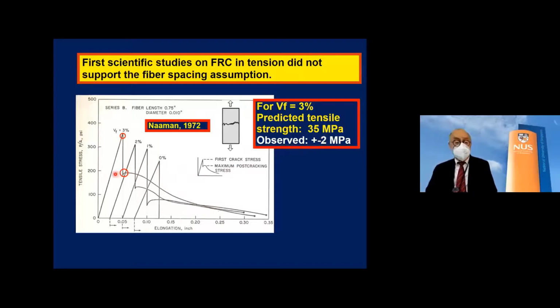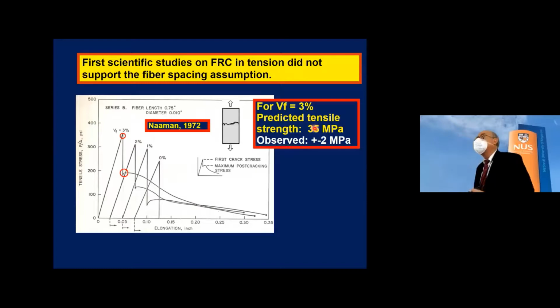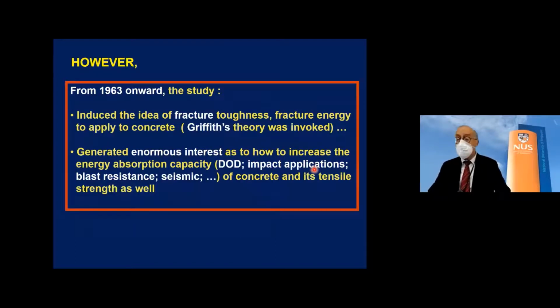I observe here, if you look PSI, about 2 megapascal, maybe 3 megapascal. But the theory of Romualdi would have given me 35 megapascal, according to my numbers. So obviously this was not correct. But because the idea of fracture toughness was introduced, because of the interest of the scientific community in getting a material that can get more fracture energy, it generated a lot of interest.